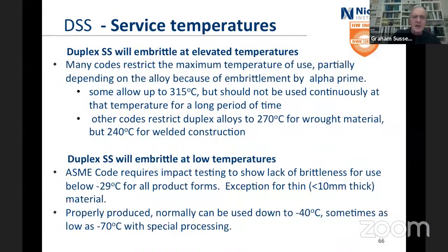Service temperatures. It's going to embrittle if it gets to high temperatures. Many codes restrict it, but mainly because of the alpha prime. ASME allows 315. Europe goes down to 270, 240 for welded constructions, which is really, really thin. You saw the picture before of duplex embrittling at low temperatures. ASME code, lack of brittleness for use below -29 for all product forms, except for thin forms. And I'm not going to go into the metallurgy of that. Properly produced, normally you can go down to -40, and you saw the example before.